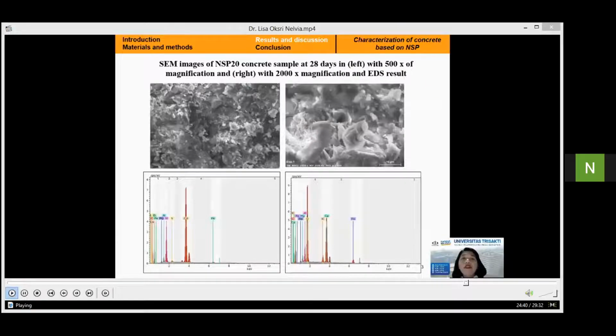After studying the properties of powders, I will now expose to you the chemical and mechanical properties of a concrete containing nickel slag powders. The figure shows the results obtained from the SEM images and EDS test on the mineral composition for NSP with a substitution rate of 20%. The EDS data result was carried out to identify the dominant elements of NSP.